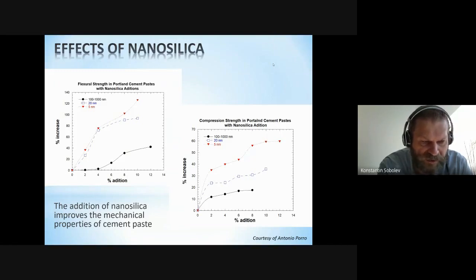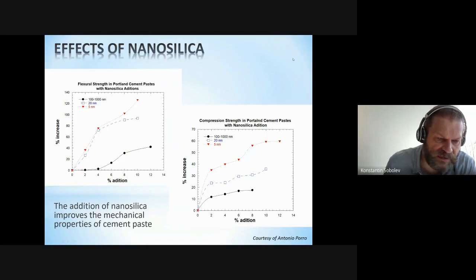Obviously, the percentage of nanoparticles here is compared to the conventional silica fume. So you can see silica fume, those are black dots. We know that silica fume starts to be effective most probably after 8%, and can be used in some applications up to 20%. And when we compare nanosilica, you can see nanosilica is really becoming effective at relatively small dosages, less than 5%, less than 10% for sure.